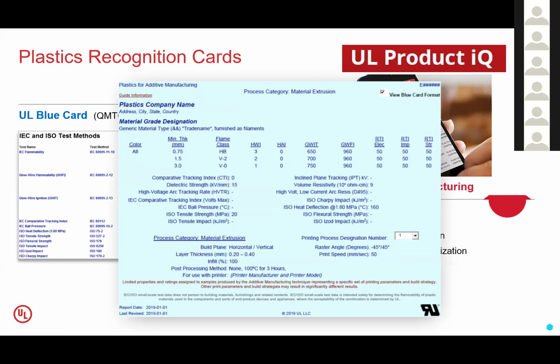Finally, is any post-processing required? Material extrusion, you might not need post-processing. Vat polymerization, if you don't do post-processing, you're going to end up with a gooey mess at some point. Finally, I mentioned the model of printer. Printer models do matter. We have found that even when we use the same parameters and the same material, we will get different results depending on the model of printer because of how they work. So that becomes a significant factor.